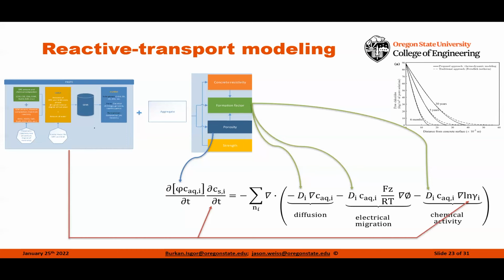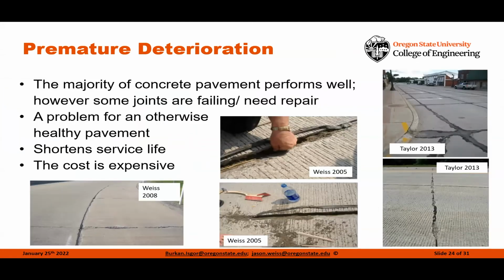All right, and I want to show one other example here where one of the major deteriorations that's happening in concrete pavements is this deterioration that's happening at these joints in these concrete pavement systems. This shortens the service life of a pavement. We get about 15 years before these joints have to be repaired, as opposed to 40 to 50 to 60 years that most people are seeing. And this is happening because of a chemical reaction.